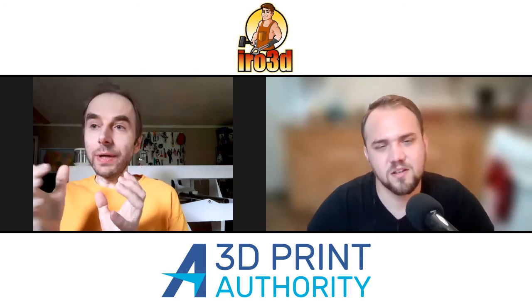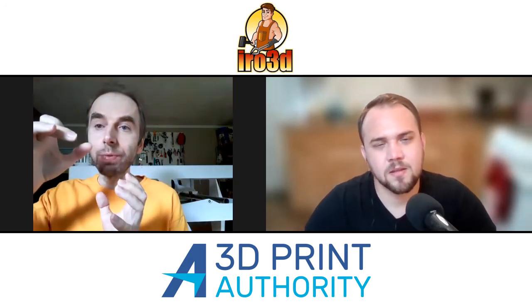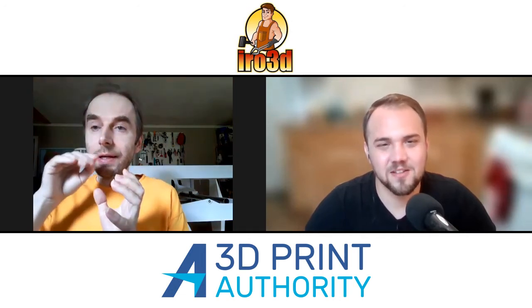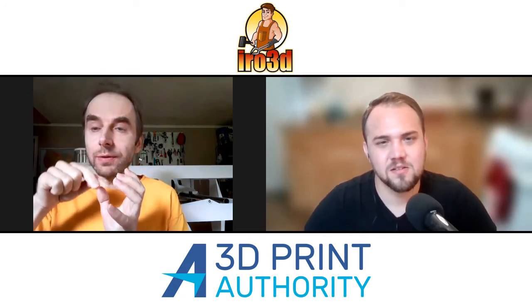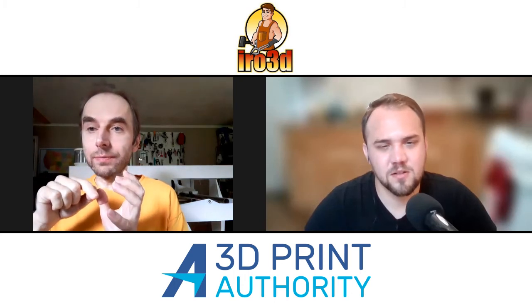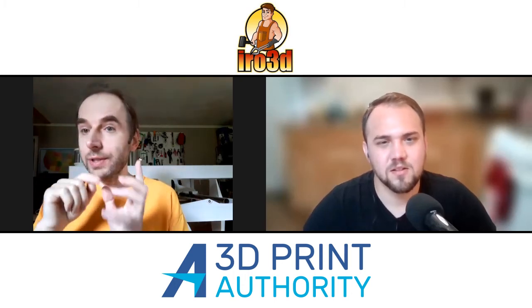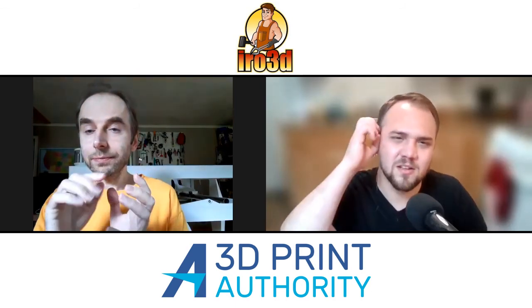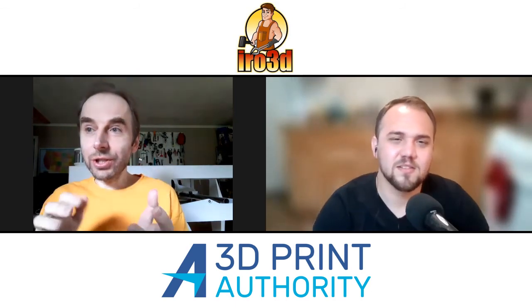Then you place a piece of infill metal on top and bake it in a kiln. The infill metal melts and soaks the metal powder. It doesn't soak the sand, because sand is not wettable by the molten infill metal. So that's it in a nutshell.